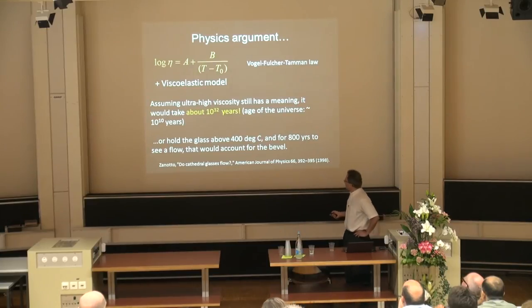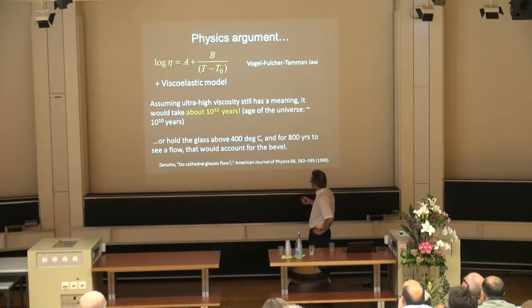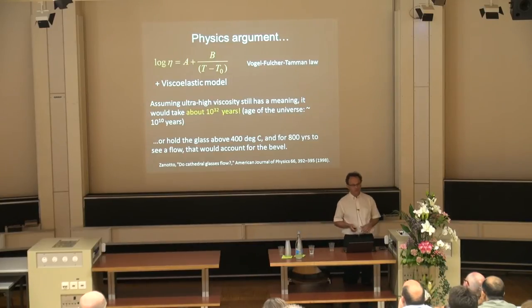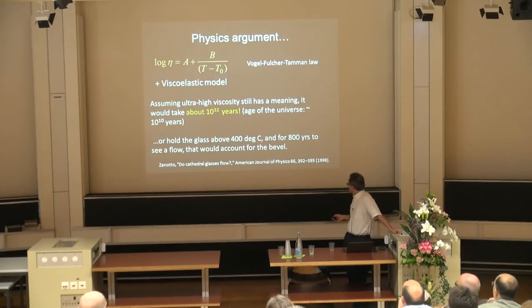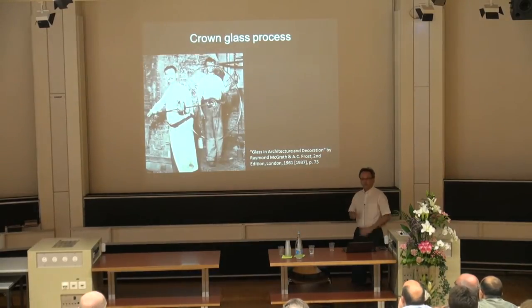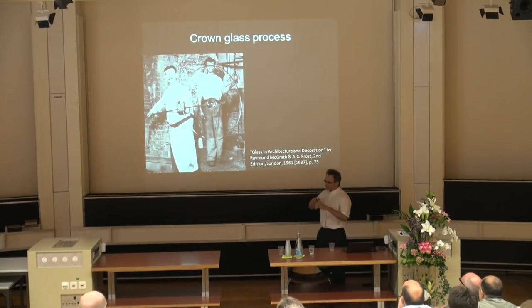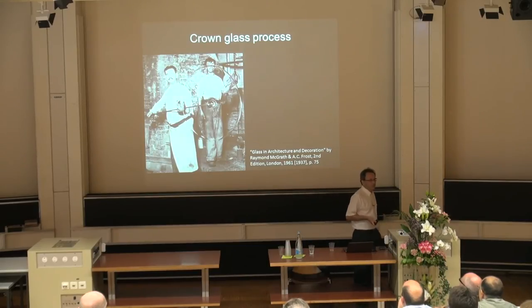And then you could say, the other way around would be to hold your glass at 400 degrees, and you wait 800 years, then okay, that may work. So obviously it doesn't work from the physics point of view. But you know, it's very vivid. And now, just to close that parenthesis, why is there this sort of non-uniform shape? In fact, it comes from the processing.